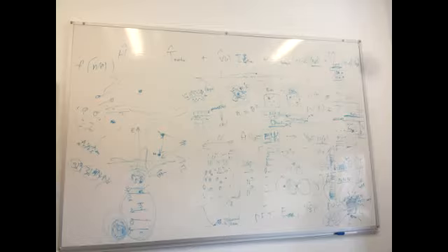But let's say I mix lithium, nickel plus manganese. Nickel oxide, manganese oxide. So nickel oxide likes one crystal structure, manganese oxide likes a completely different crystal structure. When you start mixing them, what kind of structure will you get? Will you get yet a third crystal structure, or will you get a phase separated mixture of two crystal structures? So these are exactly total energy calculations.